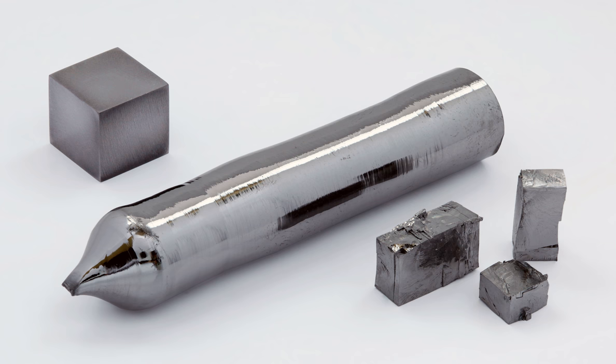Ta2O5 + 14 HF → 2 H2[TaF7] + 5 H2O. Completely analogous reactions occur for the niobium component, but the hexafluoride is typically predominant under the conditions of the extraction. Nb2O5 + 12 HF → 2 H[NbF6] + 5 H2O.